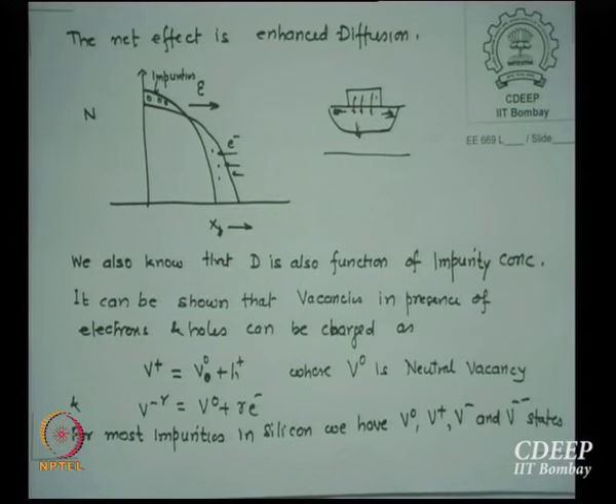So if I create the source or drain by allowing a window through which I put impurities, the source drain will not be the same size as the window I pushed through, but will also extend laterally on the sides. Sometimes that is worrying. In some cases it helps because the channel length may reduce, which is good, but in some cases it allows more depletion and more bulk charge will appear. So there are issues, VT will increase, and one has to worry how much lateral diffusion there is. If your electric field is stronger, these lateral diffusions are smaller. So the larger the doping you do, this is possible. For a normal mode of diffusion, this is not possible.